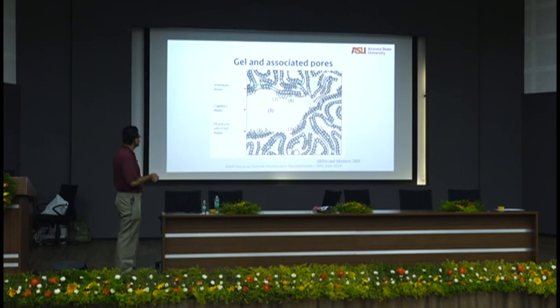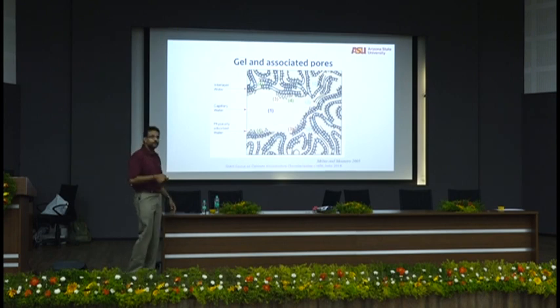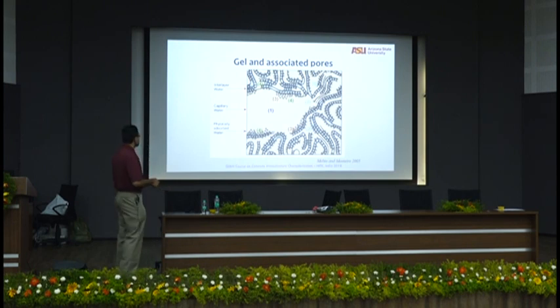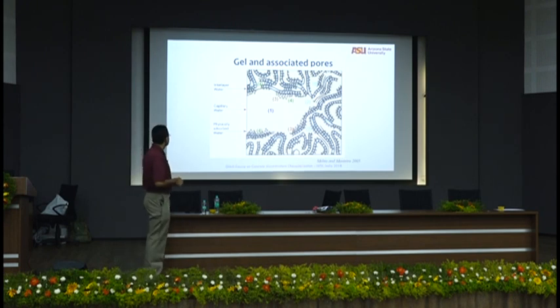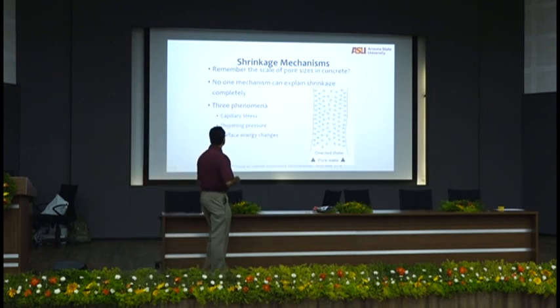2 here, these parts where you will have a lot of water that will be gone from the big zone until about 40-45% RH. 3 and 4 are generally the adsorbed water areas. Okay, and I have deliberately misplaced this 4, I should not be calling it that, this 4 is probably this pore water which doesn't have access. Gel water really doesn't go away.